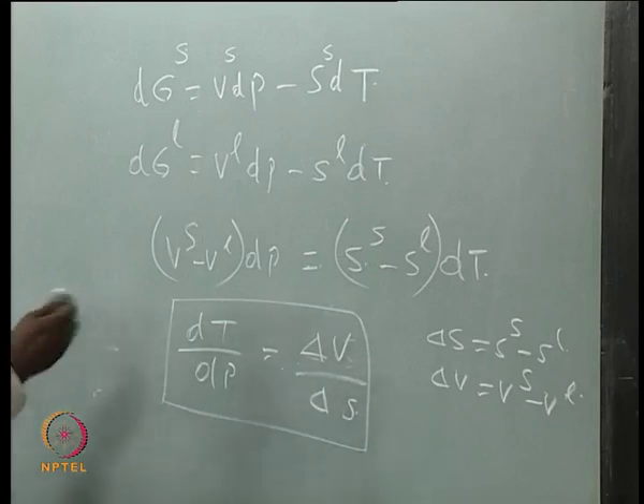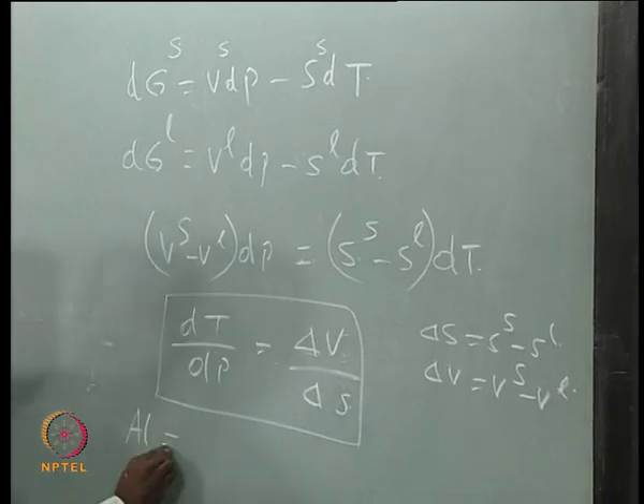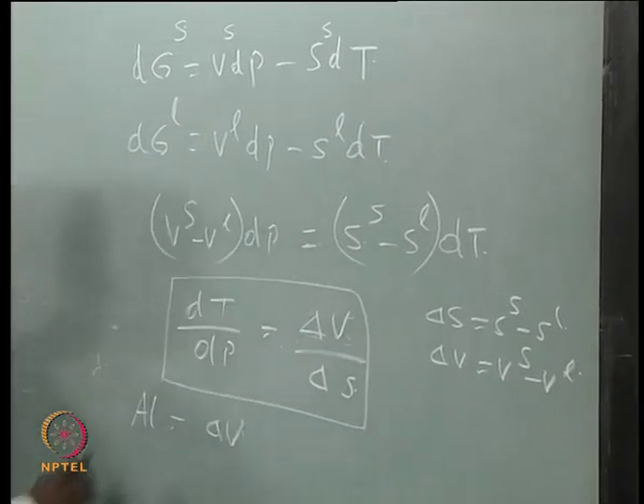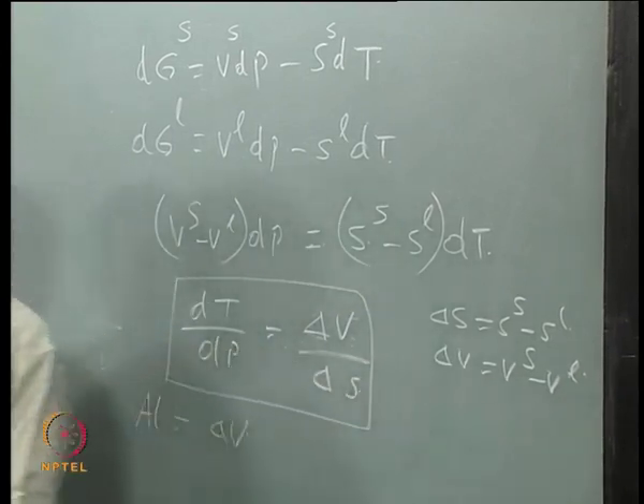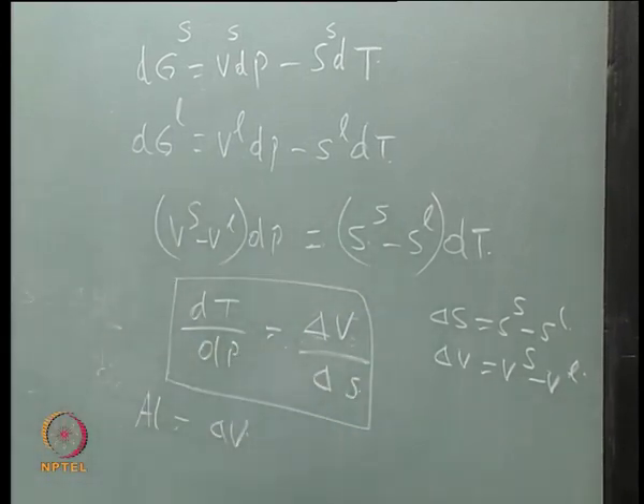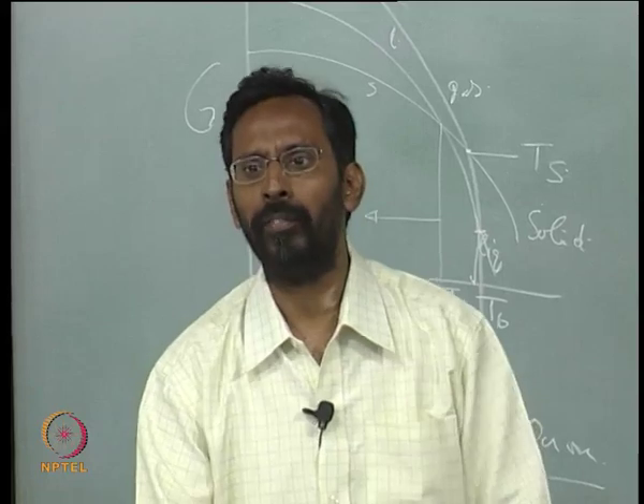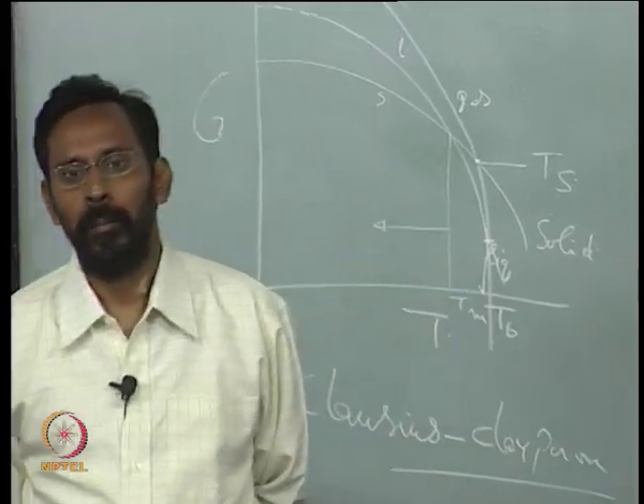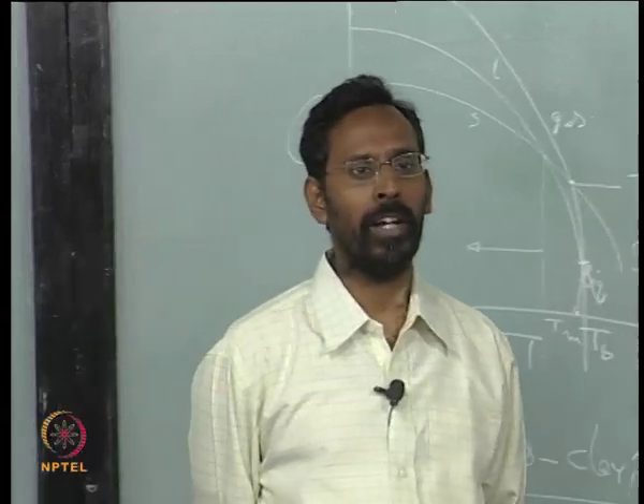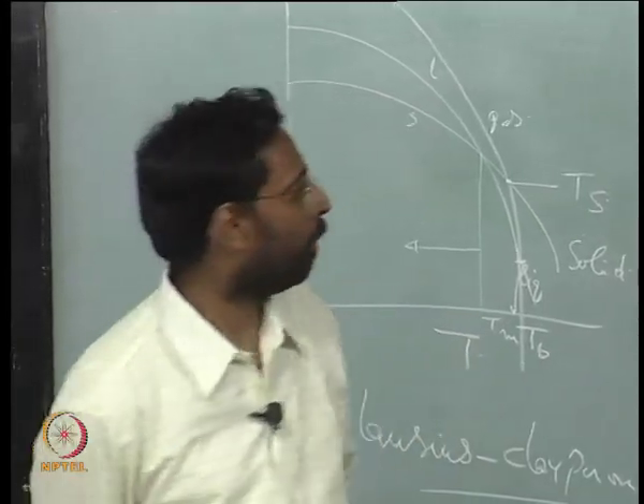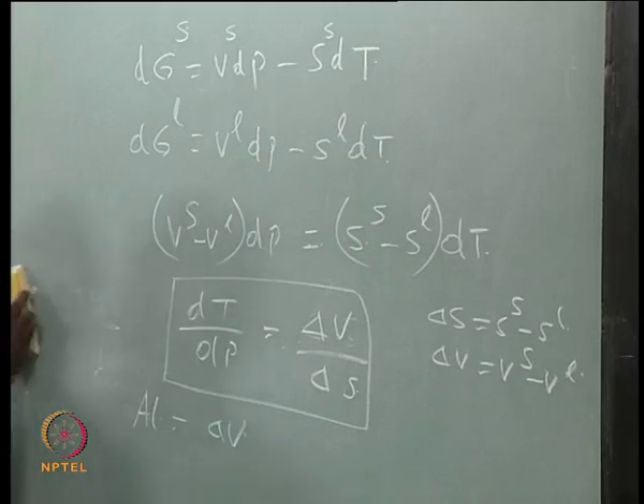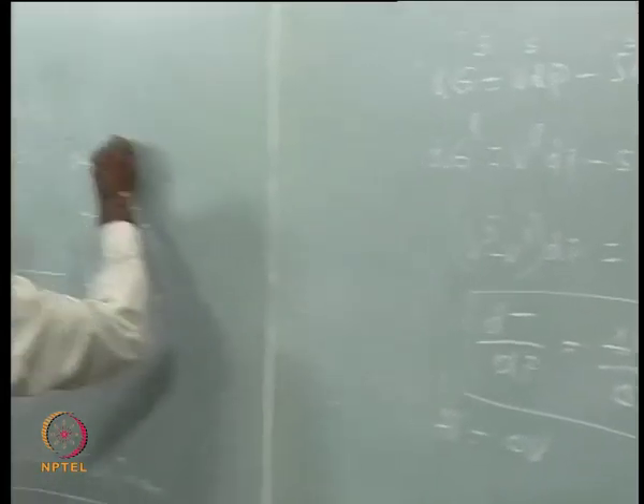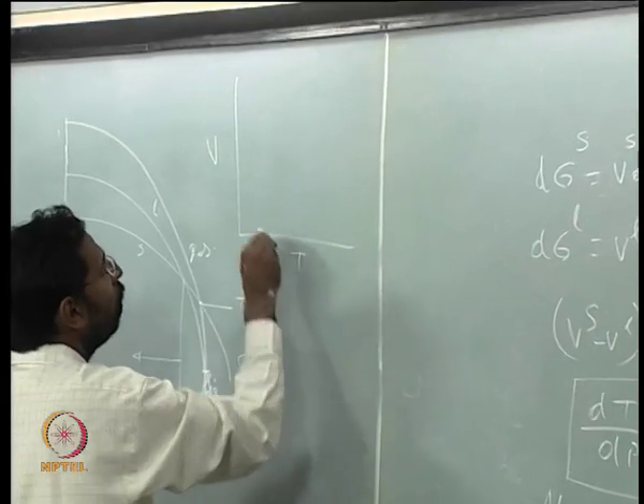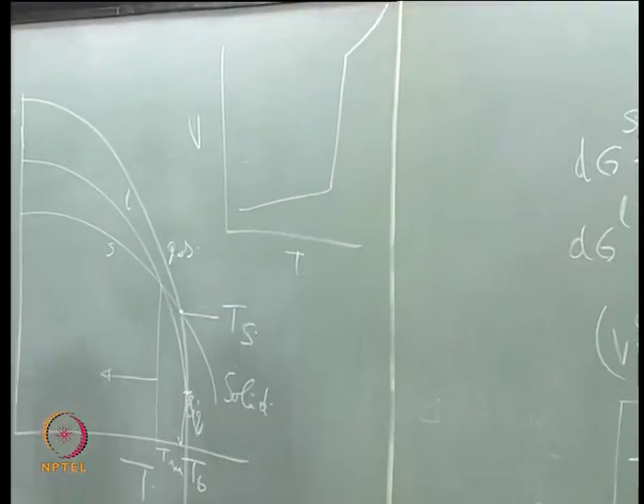For example, take up this particular case of aluminum. In case of aluminum, if I look at delta V, which is Vs minus Vl, is it positive or negative? At the melting point, if I look at the volume of the solid and the volume of the liquid, it is negative. In fact, if I plot V versus T, you would see a step like this.